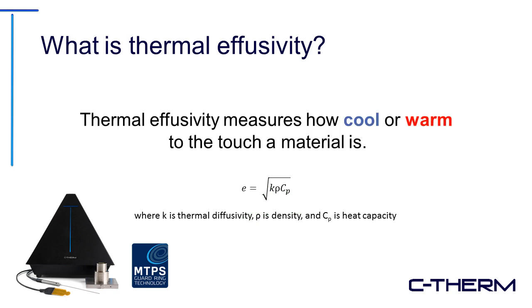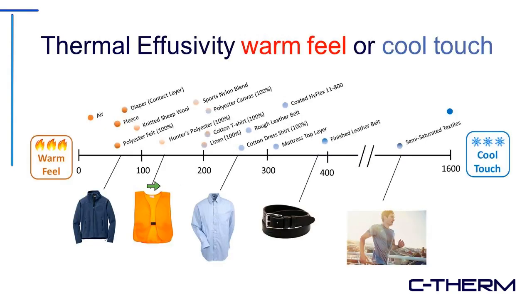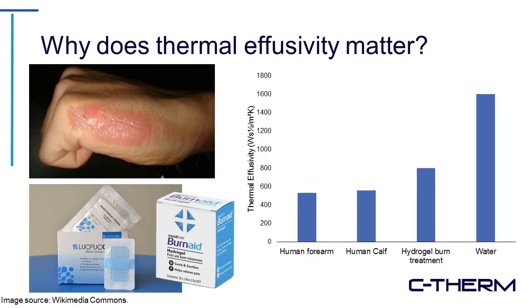But here at C-Therm, we like to look at thermal effusivity as a measure of how cool or warm to the touch a material is. So lower effusivity materials are very warm, whereas very high effusivity materials are more cool to touch. And just due to some of our testing of textiles, we can see this range, it can range quite a bit inside of different textiles themselves. So water being up here at 1600, but we have other materials like dress shirts and different cotton types of materials, which range in effusivity. And this is very important when we're looking at burn treatment.